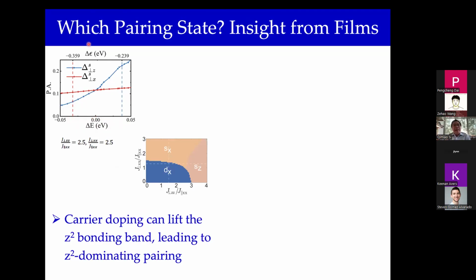So here I'm illustrating one point. Delta epsilon is the atomic crystal level spacing between the 3d x-square minus y-square orbital and the 3d z-square orbitals. Delta E being positive or negative reflects whether the bonding 3d z-square states are crossing the Fermi energy or have sunk below the Fermi energy. And just to highlight this particular variation, what consequence it could have when the dz-square orbital states are crossing the Fermi energy: because of the larger z-square interlayer coupling, it's active.